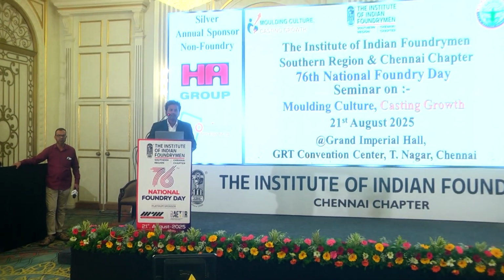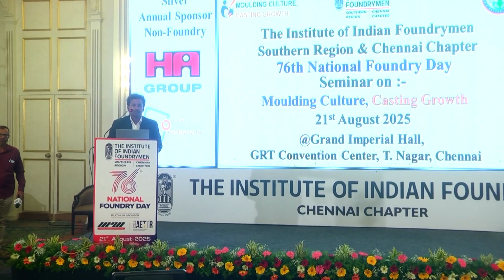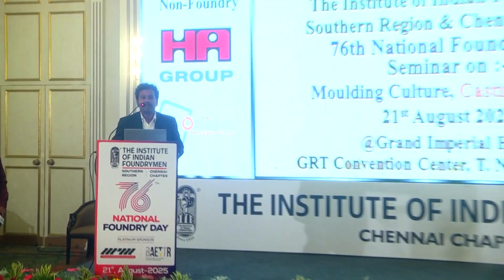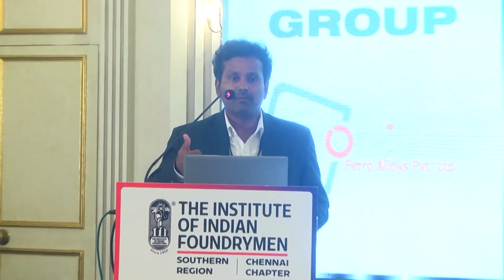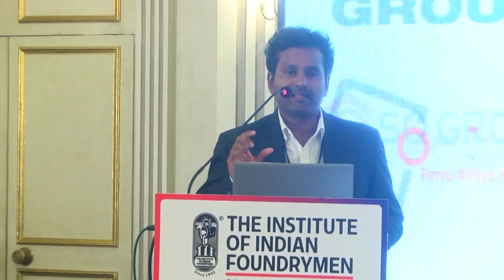Abrasion loss. Yes, sir. Actually, we add additives like silicon carbide, which will improve your abrasion resistance. There is a test where we take a specimen and sample according to the ASTM standards. So it will be injected with some abrasive particles for some particular time.